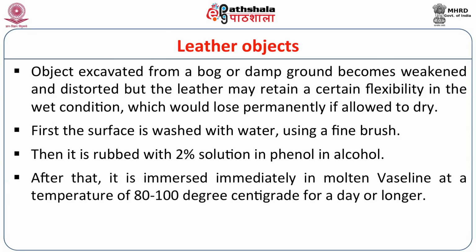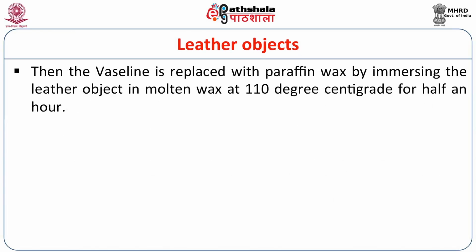After that, it is immersed immediately in molten Vaseline at a temperature of 80 to 100 degrees for a day or even longer. Then the Vaseline is replaced by paraffin wax by immersing the leather in molten wax at 110 degrees centigrade for half an hour.